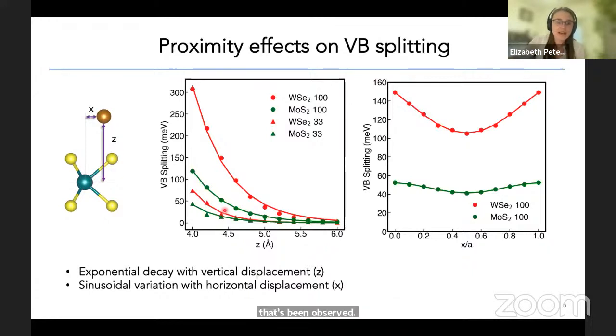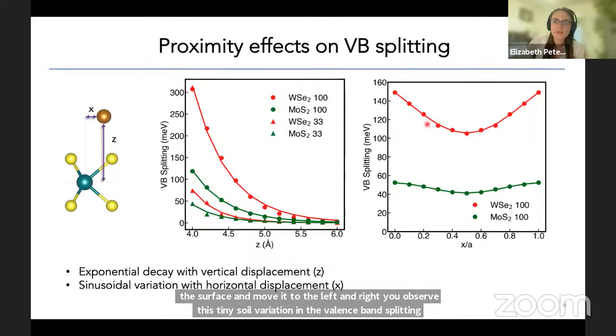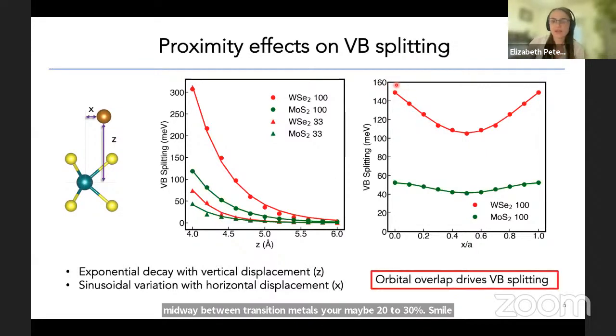And I think that's partly because the lattice parameter alignment of all of the substrates that have been studied so far isn't that great. And you can understand why that's a problem if you look at what happens when you fix the position of the iron atom above the surface and move it to the left and right. You observe this sinusoidal variation in the valence band splitting, where when it's midway between transition metals, you're maybe 20 to 30% smaller valence band splitting than when you're directly above the transition metal. And what this tells us is that orbital overlap must be a driving force behind the valence band splitting, that the proximity is really important and orbital overlap is an obvious factor in what's driving this phenomenon.